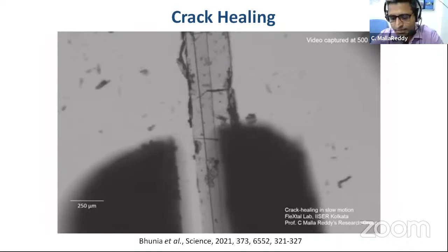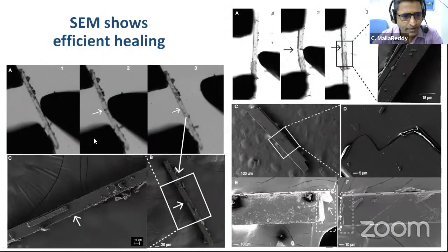You can move them, so they nicely attach to each other, even if you separate them and then bring them back again. Then we did a lot of characterization. Then we looked at under SEM. So we didn't see any sign of crack in cases where you see the perfect healing. If the healing is not good, most of the time we found a non-linear crack or some debris inside. So healing is not perfect in such cases.